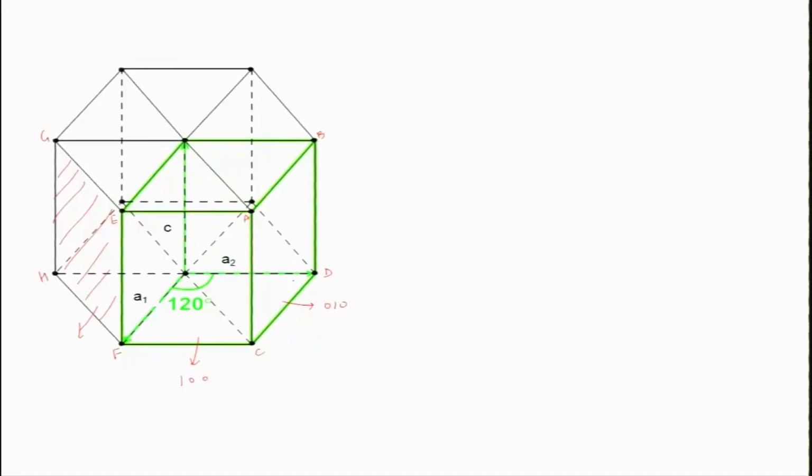So you will say this plane is some sort of 110 type plane, because you have to choose a different axis for the intercept. So this will be 1 minus 10 or minus 110. In a 3 axis system it will become 1 bar 10, but in the 4 axis system this will become 10 bar 10, this will become 01 bar 10, and this will become 1 bar 100. Now they look like a family of similar planes, and they are.